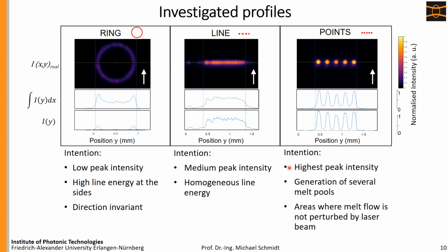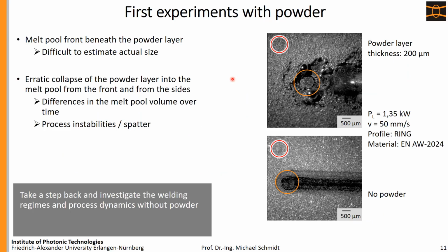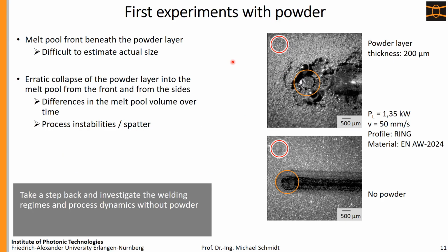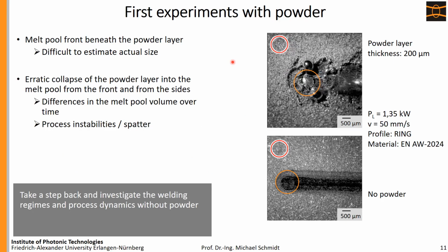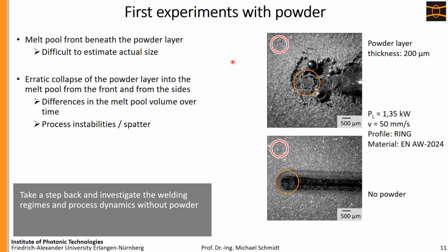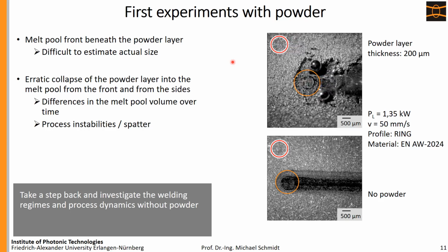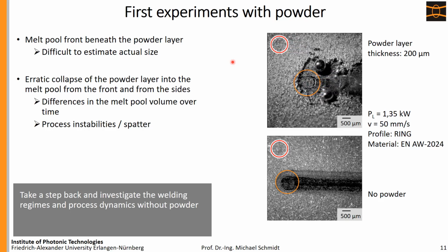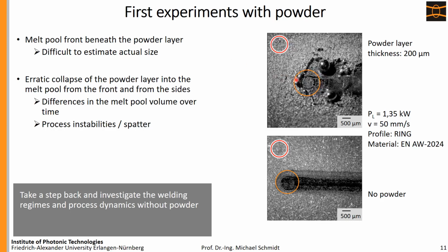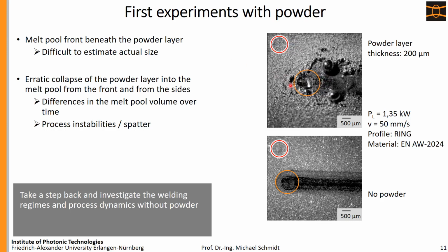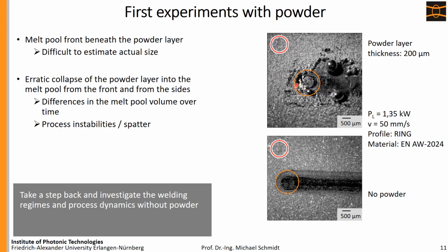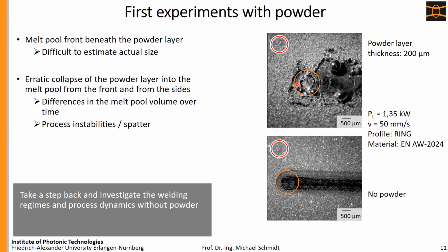Well, we wanted to see how those behave in a real process. So of course we started with a powder layer first because we want to go for additive, but we found it quite hard, as you can see from this video here, to estimate, for example, the actual size of the molten pool, because it seems the molten pool already moves forward below the powder that you can see here. So as you can see, the powder goes in and then drops in the molten zone. So this is not so easy to see what's going on here.